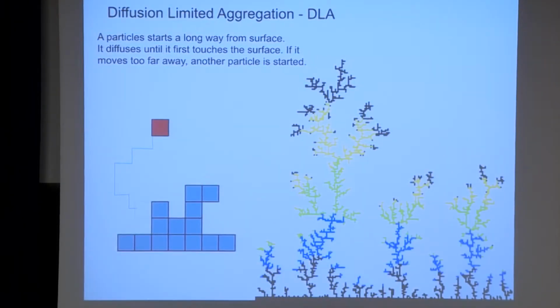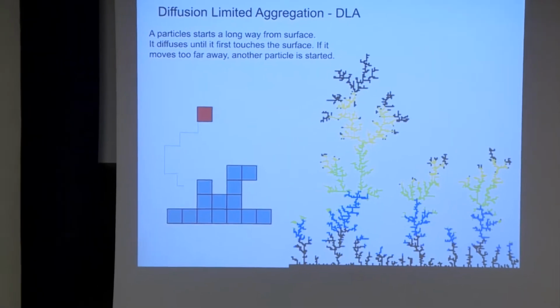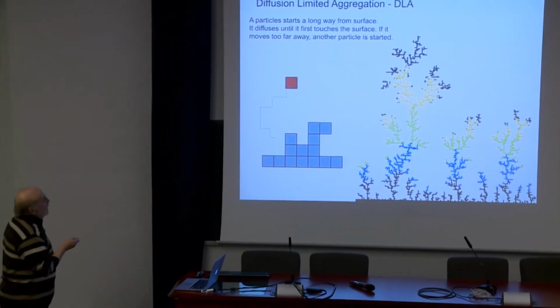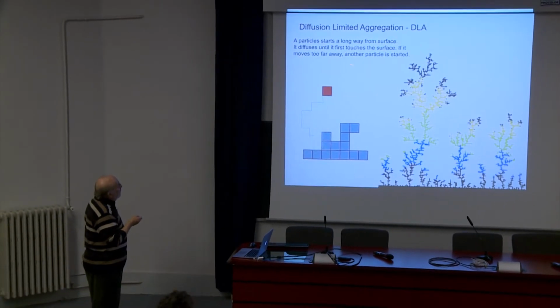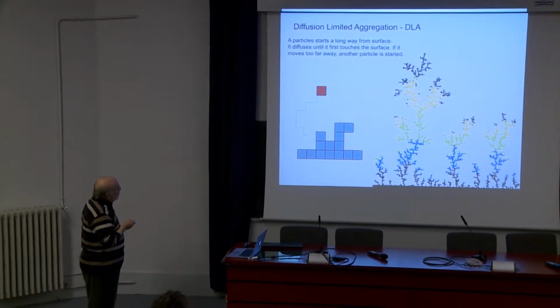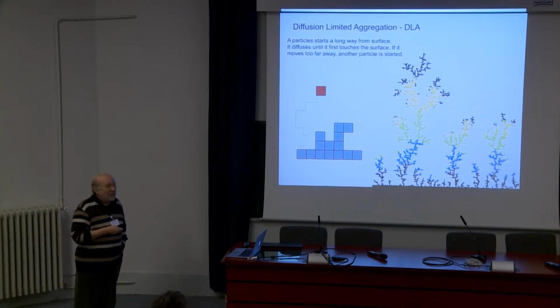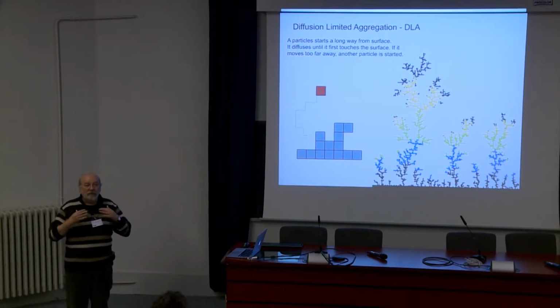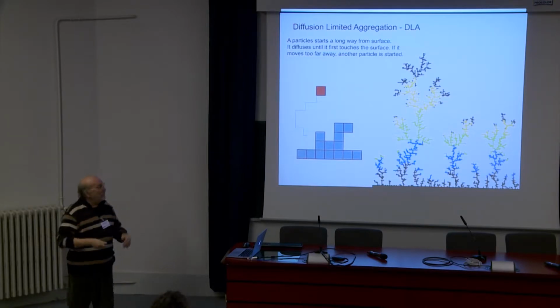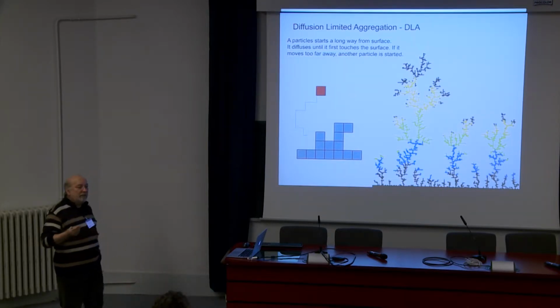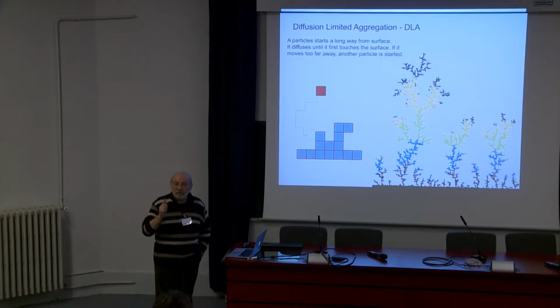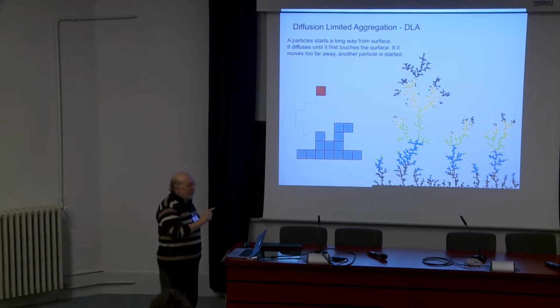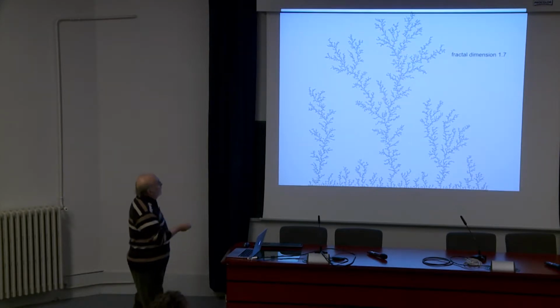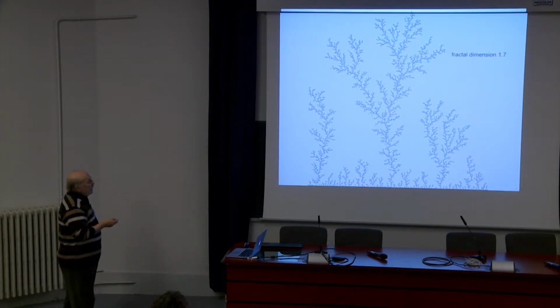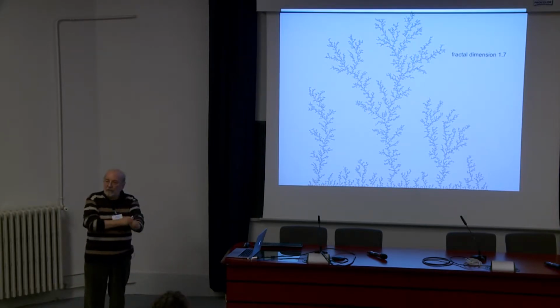And one of them is that most people think about DLA, that the pyrolusite dendrite forms just by diffusion limited aggregation. So you have a growth unit that moves quickly and then sticks with probability 1. If you have this mechanism, which means very high supersaturation, very fast precipitation, then you find this kind of dendrite, typical from DLA. Most people think that pyrolusite dendrites formed by this mechanism, with a fractal dimension of 1.7, diffusion limited aggregation, sticking probability 1.